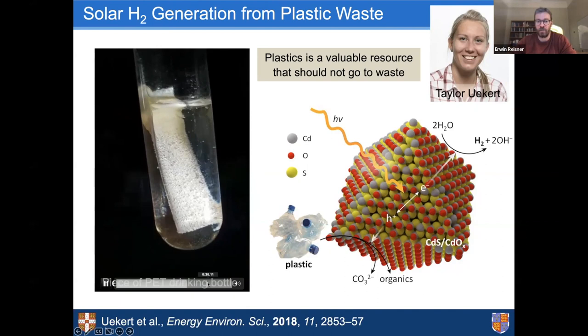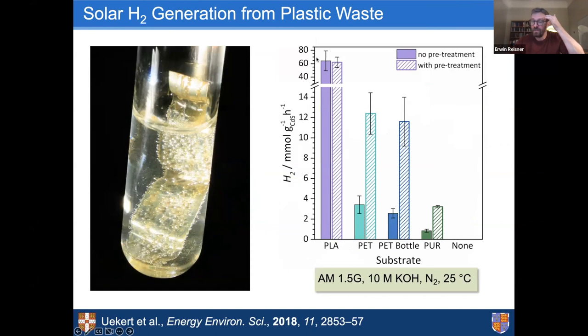This works for a number of different plastics, but in particular, it works well for condensation polymers. And that's probably no surprise, because the condensation polymers hydrolyze very nicely under the alkaline conditions, forming the monomers we can break down. In the case of PET, ethylene glycol, for example, is nice to oxidize and act as an electron donor for our photocatalytic process.